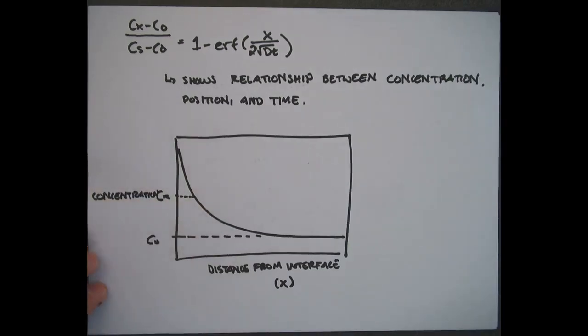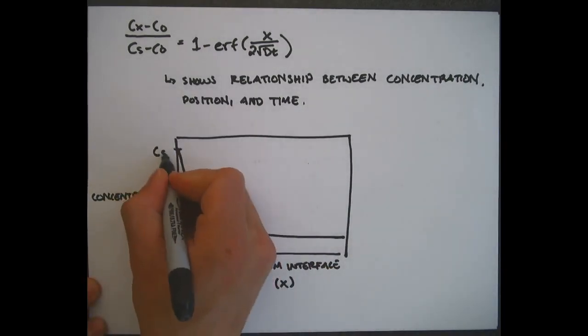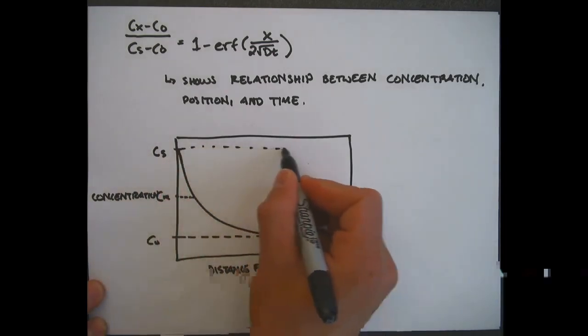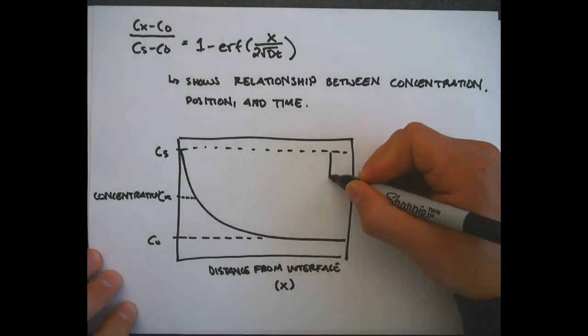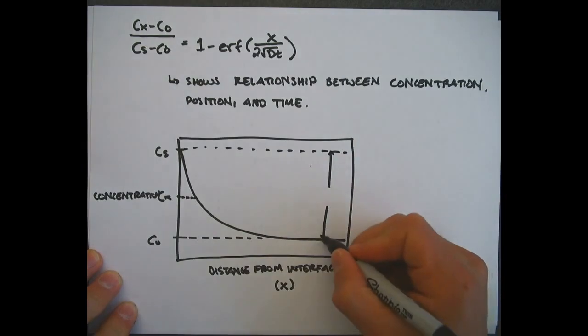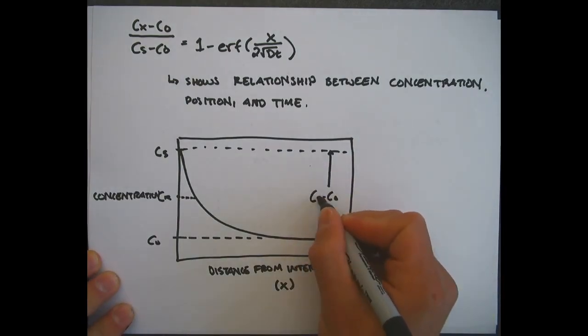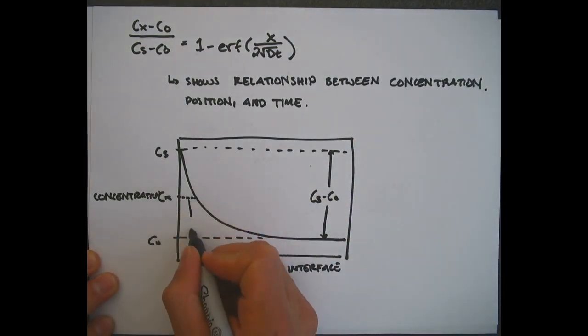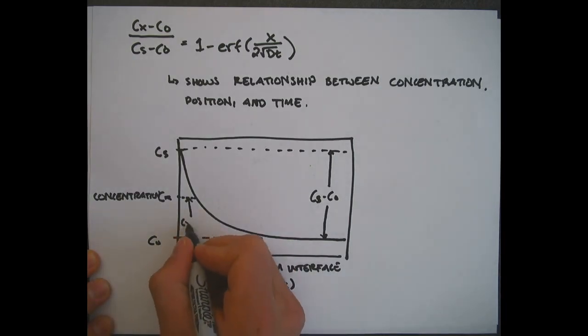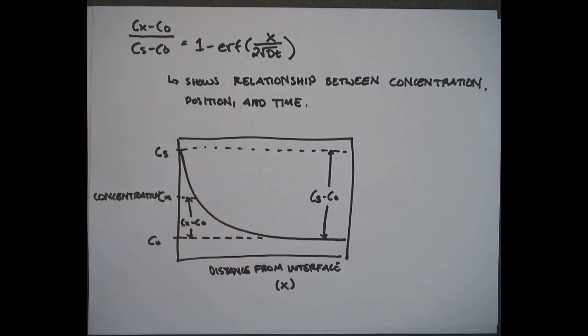Now, as you can see, the distance from the interface, when x is 0, we are at the interface, and that's our concentration on the surface. If we bring that line out and we compare the two values, what we get is C of s minus C of 0. That is our denominator. Now, we can see that the C of x minus C of 0, our numerator, is further on to the left, but we can also see that at a certain distance, x, from the interface, we have another different concentration. We're going to look at an example problem now, right out of the Callister textbook.